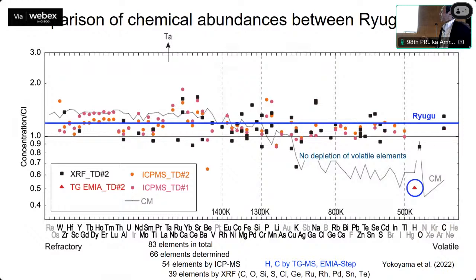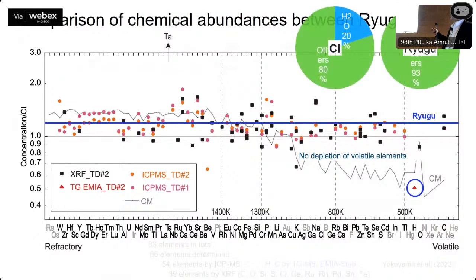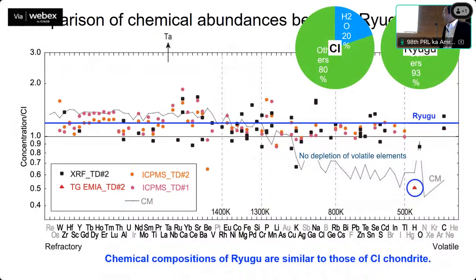But the average is above the CI meteorite value, at 1.2. This is because hydrogen is depleted. Hydrogen of Ryugu is 7%, and CI is 20%. Therefore, the concentration of Ryugu is uniformly upgraded to 1.2. So we conclude the chemical composition of Ryugu is similar to that of CI chondrite.